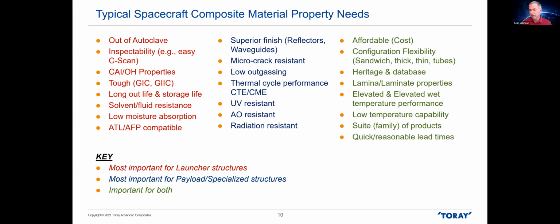And kind of underlying micro crack resistance is the thermal cycle performance, the coefficient of thermal expansion and moisture expansion. All composites absorb some moisture, and that's why these materials that were selected are actually very key. They absorb very little moisture, hence they have very little moisture expansion. And a lot of these materials too are very, very low CTE, close to zero, over the types of temperature ranges that Ben was describing in his